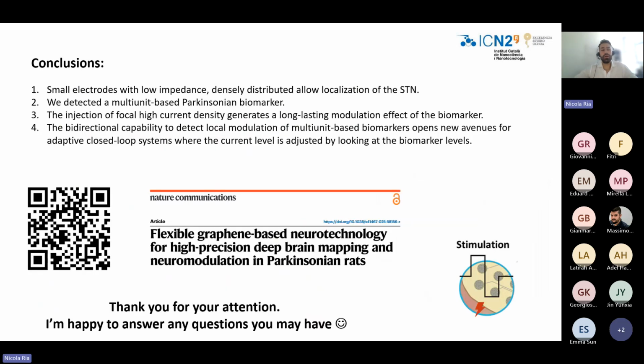So to summarize, small electrodes with low impedance and densely distributed allow the localization of the subthalamic nucleus where deep brain stimulation is applied. We were able to detect a multi-unit based Parkinsonian biomarker, and by injecting high density charge, we were able to produce a long-lasting modulation effect of this biomarker. This bidirectional capability to detect and modulate the biomarker opens new avenues for adaptive closed loop systems where the current level is adjusted by looking at the biomarker levels.